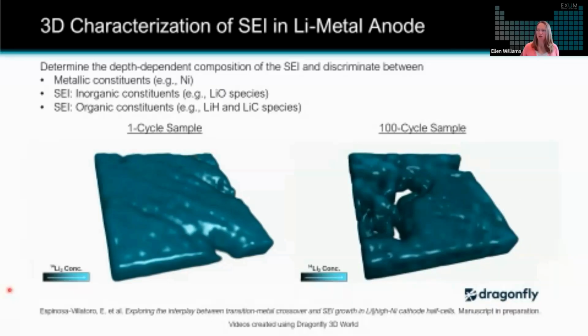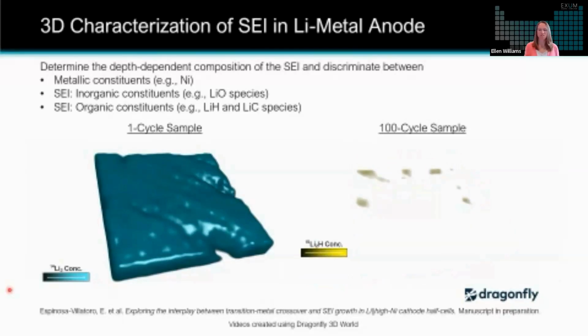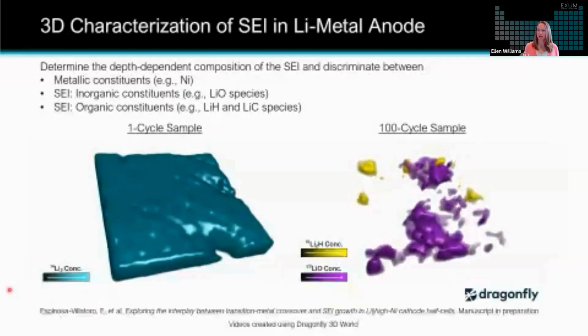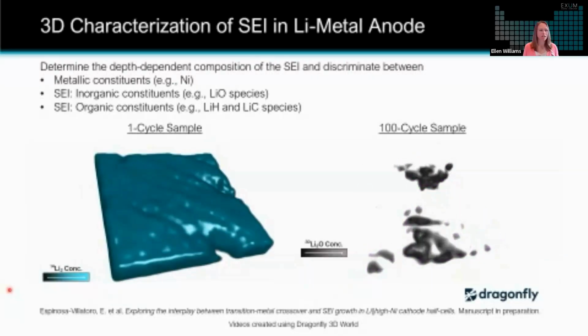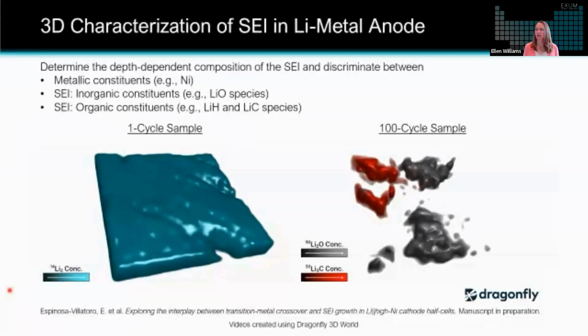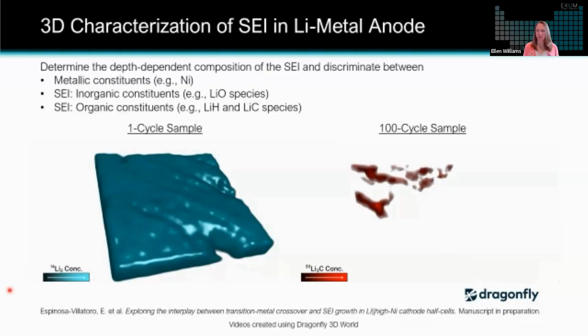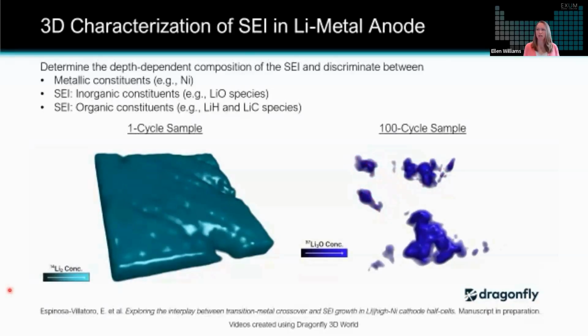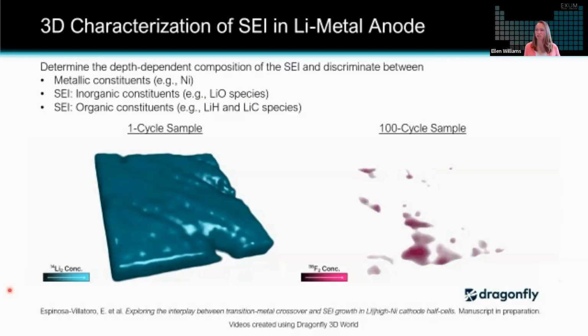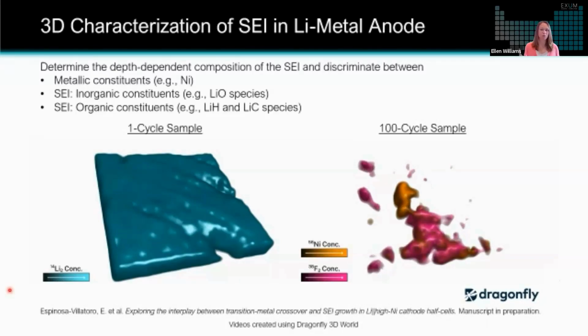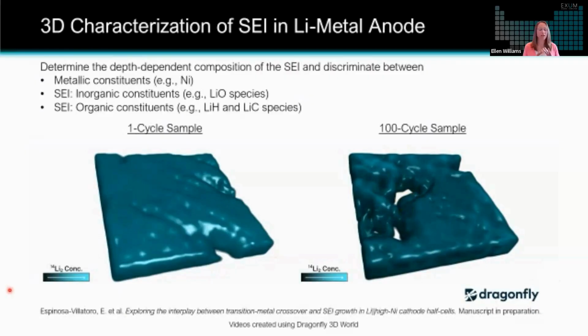And now I'll play you the video of the 100 cycle sample. So this is the same analysis, the same 1.5 mm area done with 5 layers. But what we're identifying here is as we start to see these different species that are representing the SEI, we see a much denser SEI has formed after these 100 cycles. So we're seeing, once again, a difference in where the inorganic versus the organic species are concentrating, but overall, a denser picture of SEI formation after this 100 cycle sample. And then eventually we see also where the nickel migration is concentrating as well. So again, not going to reveal all of the findings of this study.